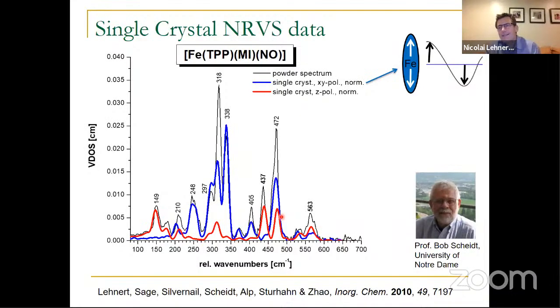So you can do experiments like this. We have linear polarized light coming from our light source, from the synchrotron, and we can take the crystal and rotate it in a way that the plane of the heme lines up with the direction of oscillation of the electric field vector, right? When we do this, then only vibrations get excited, or scatter, or contribute to the spectrum where the iron moves in the plane of the heme. And that gives that spectrum shown here in blue. Then we can rotate the crystal and measure again. Now we're perpendicular to the direction of polarization of the incoming beam, and now only vibrations can contribute where the iron moves out of the plane of the heme.